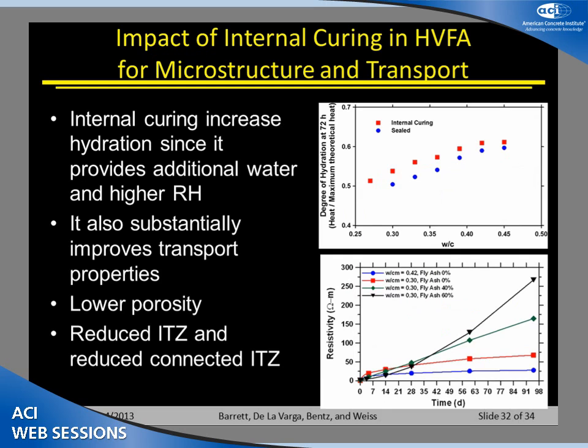Okay. And the reason for this is shown on this plot up here. This is just the heat that's given off, which is a measure of how much material is reacted versus water to cement ratio. Sealed system, internally cured system at 3 days, you're getting about 5 to 10% more of the material reacting because you're supplying water to the system. This gap gets bigger and bigger over time when you've got more things like supplementary materials in the system. So keeping water in the system, keeping the system hydrated, does exactly what we're taught in Concrete 101, keep curing the concrete, but we're curing it from the inside out.